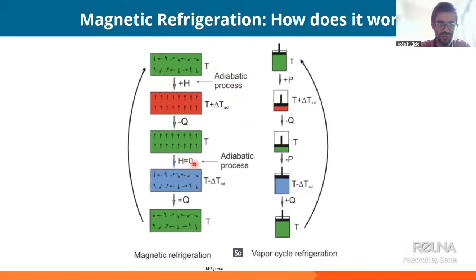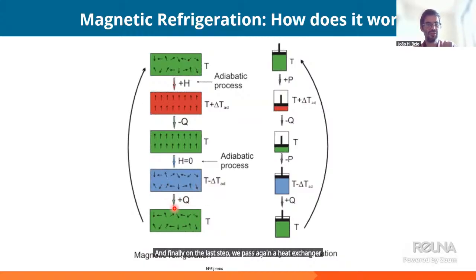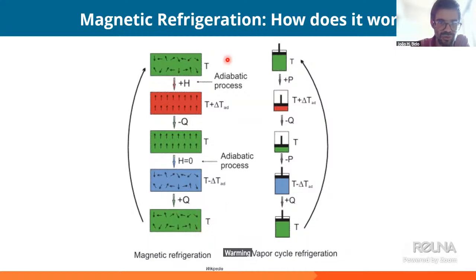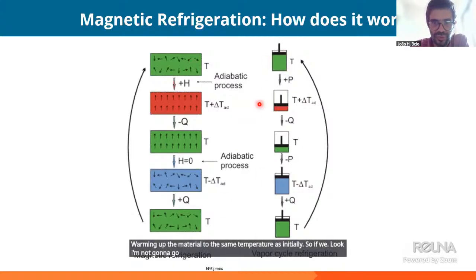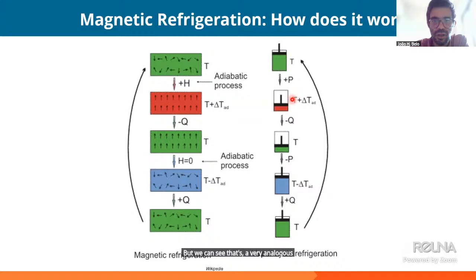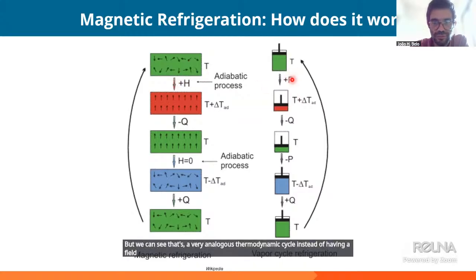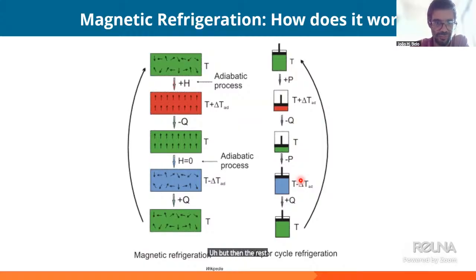So now we remove the field, that's why this H equals 0, and we get a cooling of our material. The temperature of our material drops. And finally, on the last step, we pass again a heat exchanger, which basically is going to transfer the heat from the inside of our refrigerator to the magnetocaloric material, warming up the material to the same temperature as initially. So I'm not going to go into so much detail on the vapor cycle, but we can see that it's a very analogous thermodynamic cycle. Instead of having a field, we have a pressure, but then the rest is basically the same.